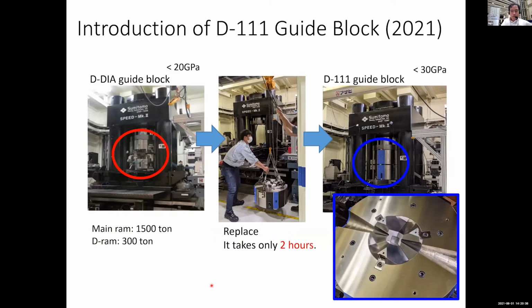We have already introduced the D111 type guide block this year. We made the mold replaceable with the existing D-DIA, and it can be replaced in just 2 hours. We have already confirmed that it is possible to perform deformation experiments at up to 30 GPa.